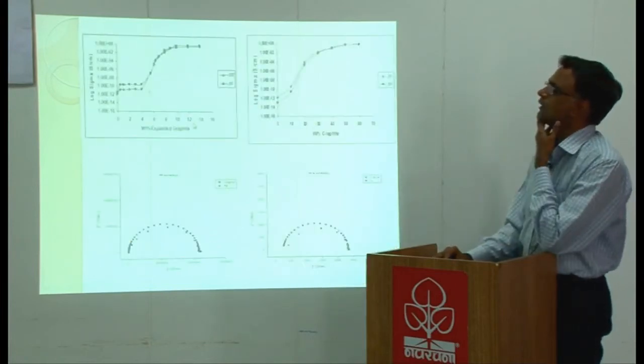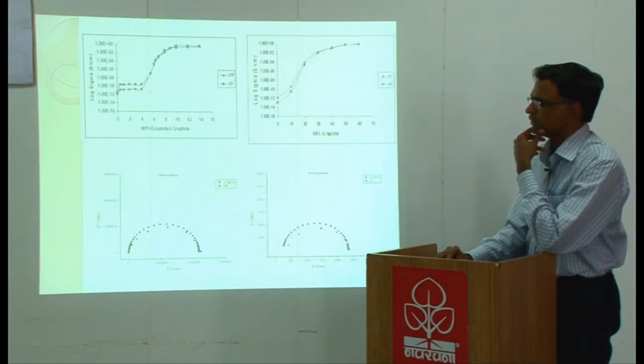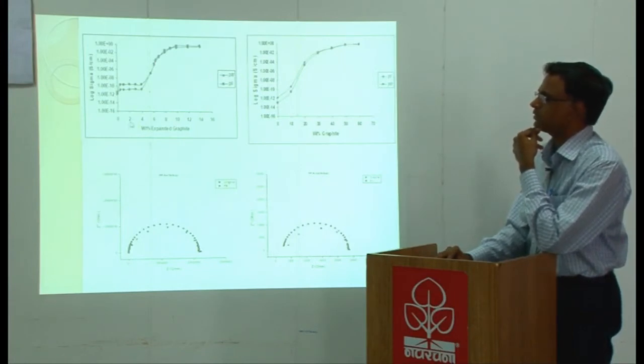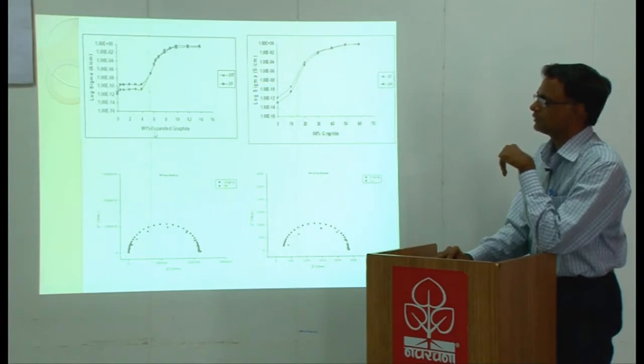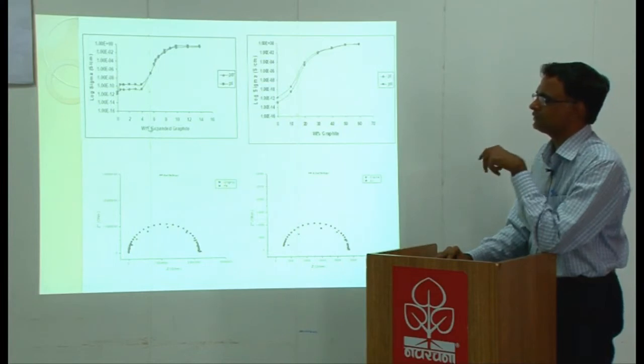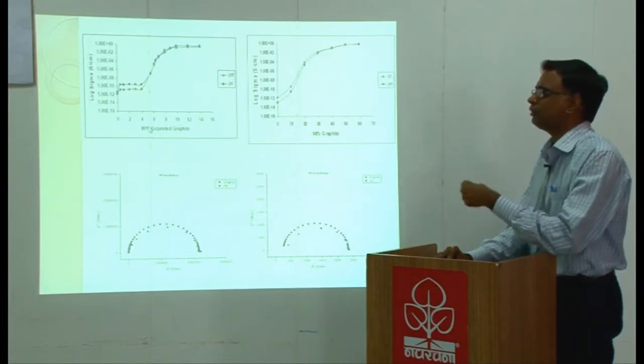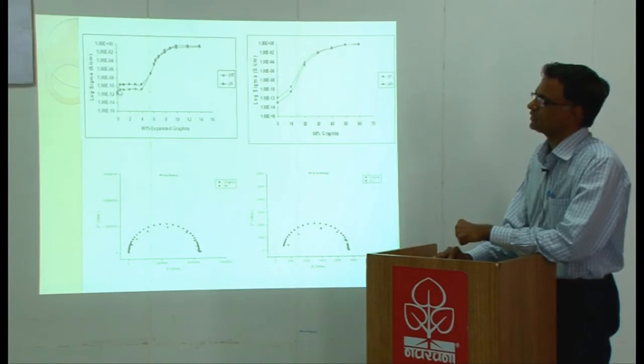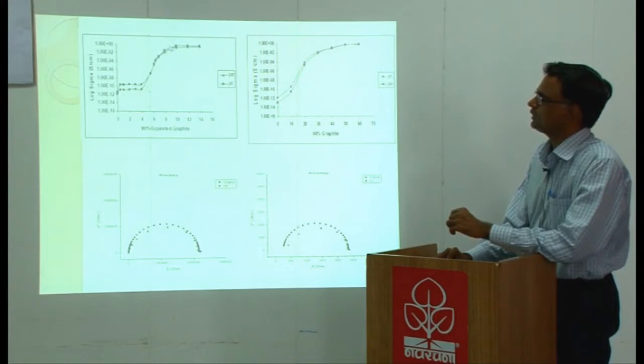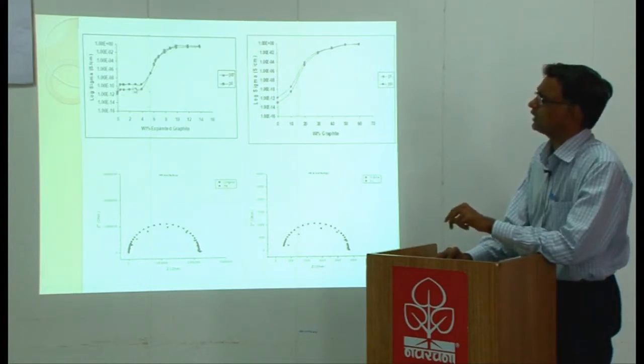This is the typical electrical conductivity variation which has been measured with PP. In PP, you vary the concentration of expanded graphite from 2, 4, 6, 8 like that. The expanded graphite is first sonicated in 100 ml of acetone and then mixed with PP and dried, and you powder mix it and make pellets, measure the resistance, calculate the electrical conductivity, and you get a nonlinear variation. So this shows a bit of anisotropy in plane and through plane.